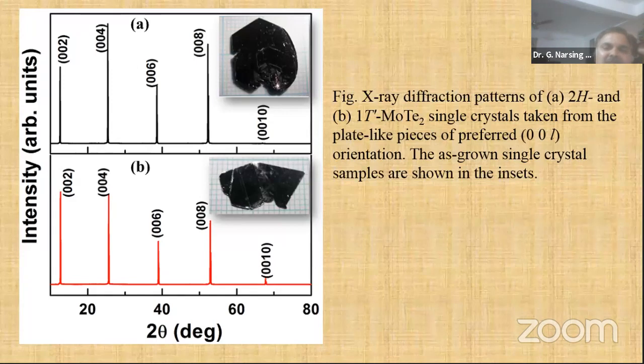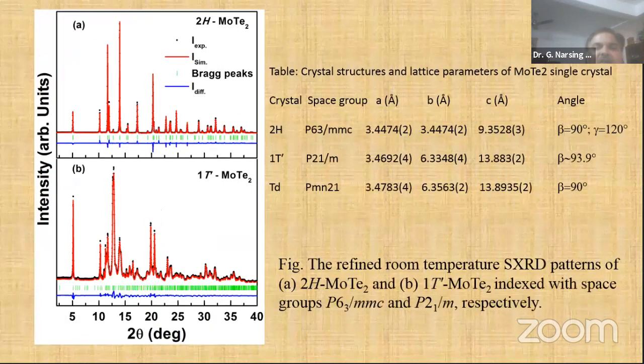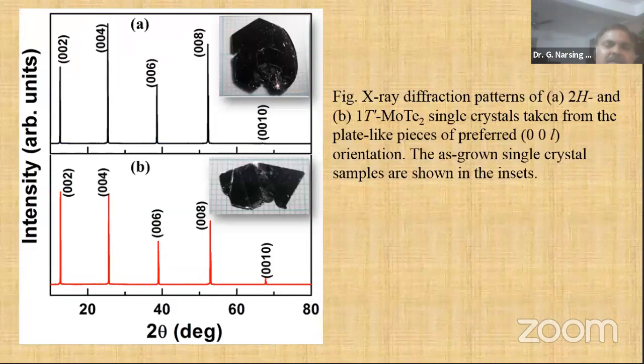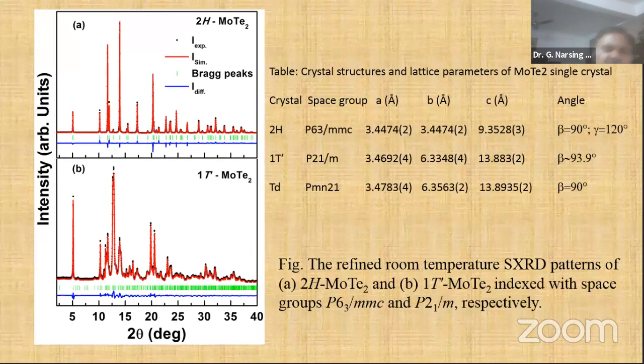So initially maybe we did like that also. We don't know exactly. Later on, once the papers came, we thought, hey, we already measured and made the sample, but we didn't get that type of property. Then we went through it in detail and got a different type of result. You can see the powder diffraction: the same crystals we grind, this 2H and 1T prime. We grind these crystals and get the powder diffraction, also with synchrotron X-ray diffraction.